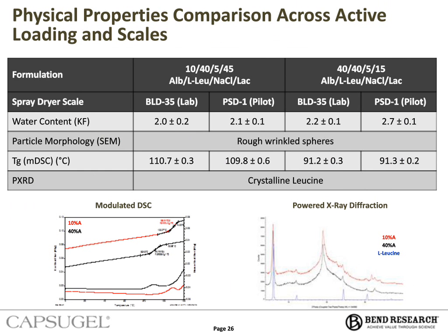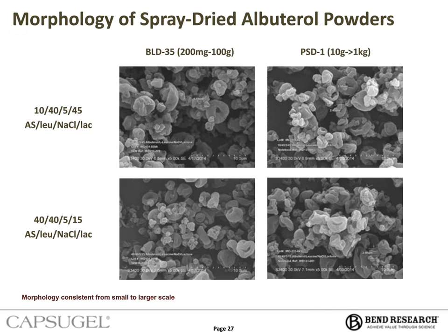So slide 27 just shows the SEM images, as everyone likes to look at the actual pictures of the spray dried particles. So again, with the 10 and 40% active loading in the two different scales, we see very similar particle morphology and particle characteristics. And what we do see here is this kind of shriveled raisin morphology, and this is really a function of the leucine used in the formulation, hence why it's added into here. These particles with the more wrinkled morphology limit surface-to-surface interactions between the particles, and like mentioned earlier, are well documented to improve aerosol performance.